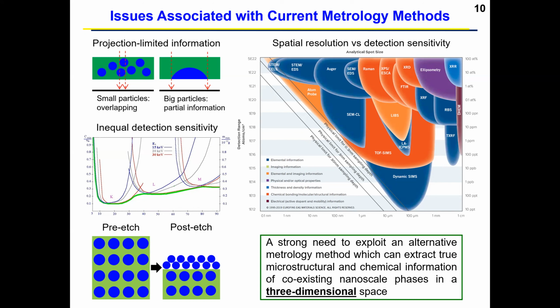For nanocrystalline precipitates smaller than the thickness of the cross-sectional TEM specimen, the electron beam penetrates both the precipitate and the surrounding matrix, thereby collecting the integrated signal coming from the two phases. For precipitates larger than the thickness of the cross-sectional specimen, the precipitates seen in TEM images are sliced views of a portion of that feature, omitting the key morphological information. These two situations are very briefly shown in the two illustrations on the top left.